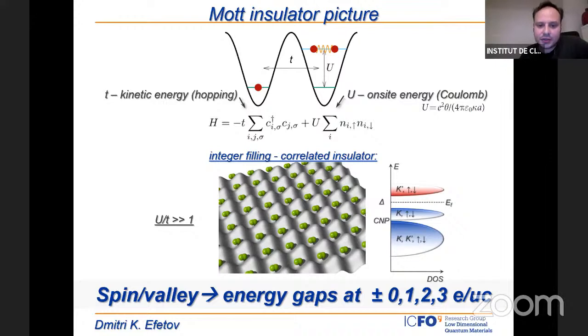Whenever we have such a condition, it costs a lot of energy for electrons to hop between different lattice sites. And what happens is that we basically obtain an insulating gap, and this insulating gap is due to the interactions. I also want to mention that because we have all these conditions, we have gaps developing at 0, 1, 2, 3 electrons per unit cell.